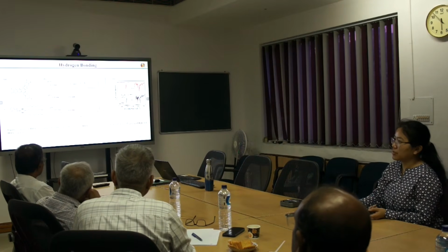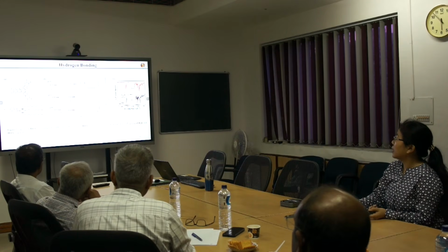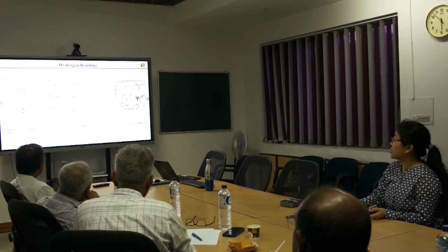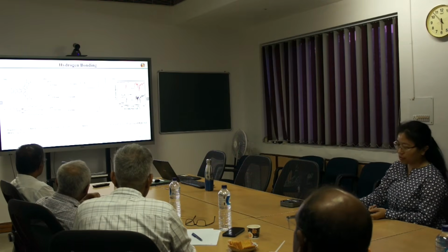So this further confirms the presence of hydrogen bonding in the BQA molecule. And also in the BQE molecule, which did not have hydrogen bonding, which did not have NH amide bonds, the carbonyl stretching frequency was observed at 1733. So the carbonyl stretching frequency observed for the BQA molecule was lesser. So this further proves the presence of hydrogen bonding in BQA.